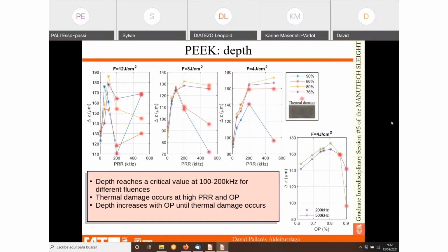Okay, but if we decrease the overlap ratio, then, as we can see here at low fluence, even if we are working with 500 kilohertz, we don't get this thermal damage. So it will be interesting to play with a low overlap. That can also be seen here, where we have an increase of depth with the overlap until again a critical value, then it drops again. Okay, same tendency.